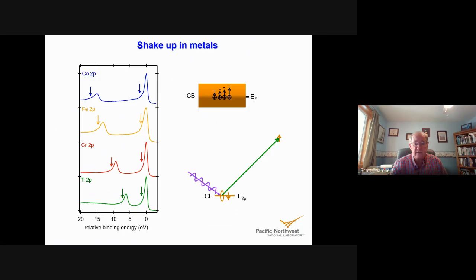I show that schematically here. Because you've got unoccupied states in a continuum above the Fermi level, you can pump electrons up to those different unoccupied states over a range of energies. And so instead of getting a discrete feature some eV away, you just get a manifold of features all on the low kinetic energy or high binding energy side, and that makes the peak look asymmetric, as you see here.